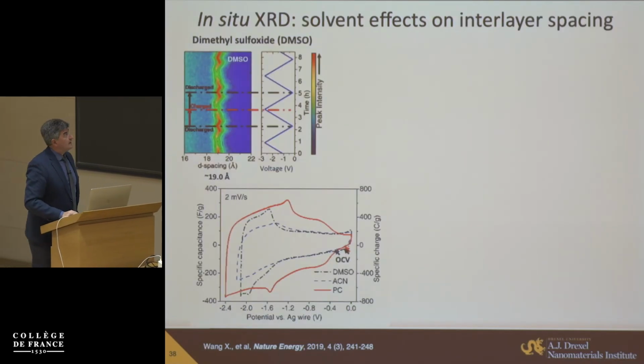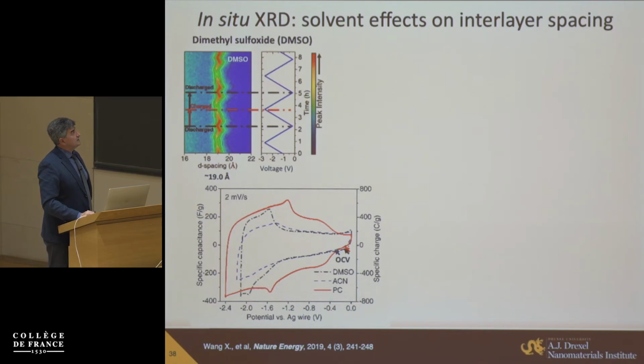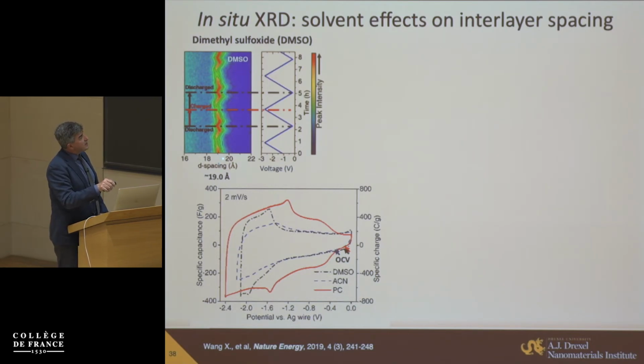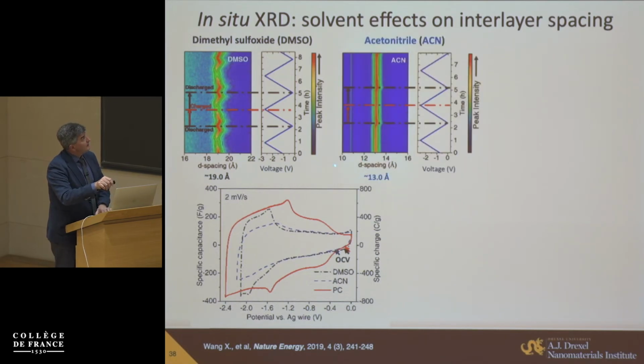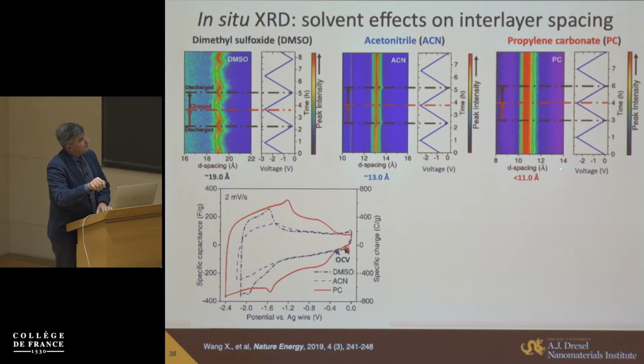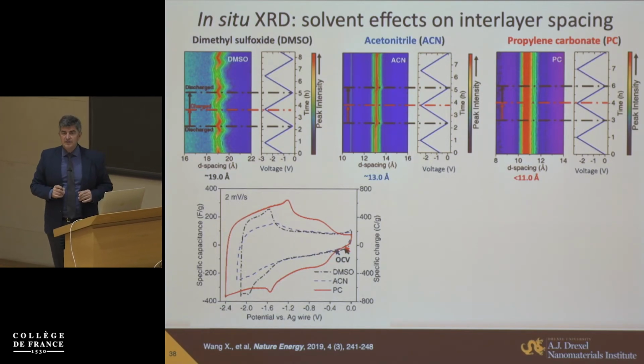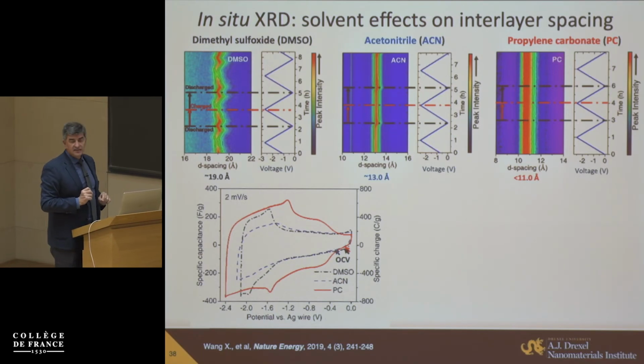So why does it happen? We looked at the intercalation process, and this was work done at Toulouse using in situ XRD. What you find is that in the case of DMSO, there is a large interlayer spacing of about 19 angstrom. In the case of acetonitrile, it goes down to 13, and in the case of PC, it goes down to 11 angstrom. With a 9.5 angstrom thickness of the titanium carbide layer, we get basically only about an angstrom in between.